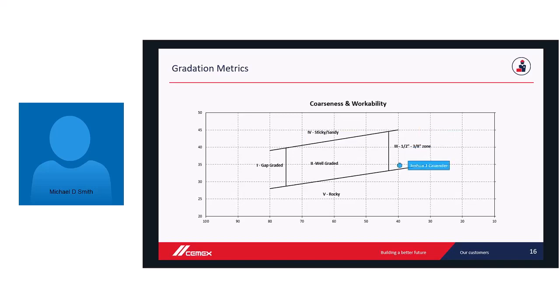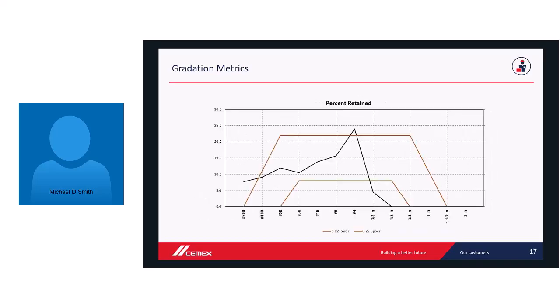And then over here is your 3/8 and half-inch zone. This is where typically a 3/8 mix would land, or a half-inch mix. And if you're in this zone, you have to be concerned with gap grading issues. So that's how this one works. A lot of studies and research tend to show that this is not very accurate. The charts we're going to look at next tend to be more favorable based on a lot of the testing done. It's shown that the results you get in the field don't correlate as well with this chart as with some others.